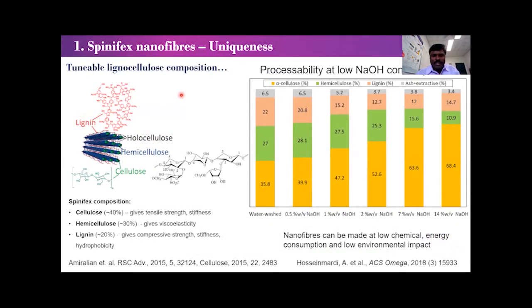The other thing about the lignocellulose resource, where we have lignin, hemicellulose, and cellulose, is that we can tune the composition internally, in the bulk, and also at the surface. What this implies is that when you have a high amount of lignin, it becomes less hydrophilic. When you remove lignin and hemicellulose completely, it becomes more hydrophilic and polar. So that functionality we can change.